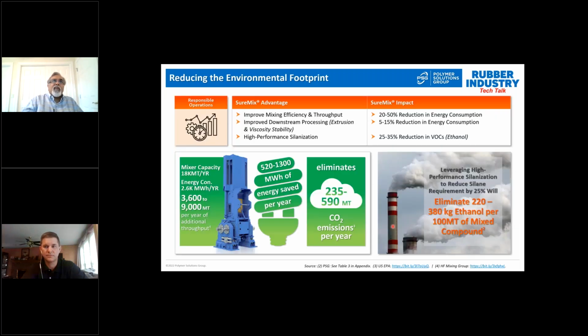Let's look at mixing and processing efficiency. The feedback that we have at the factory scale is a 20 to 50% reduction in energy consumption in the internal mixer. That is driven by two factors. One is fewer mix cycles. Especially highly loaded silica compounds have to be milled multiple times to get the viscosity in an acceptable range and get the micro dispersion to an acceptable level. With SureMix, you can have a dramatic reduction. The second is the lower viscosity.